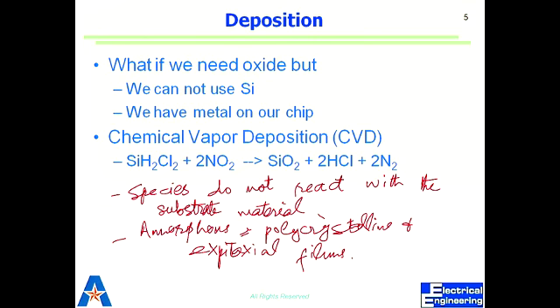This again, upload it here. We have looked at oxidation, right? This is just an example: if you want to have silicon dioxide but we cannot use silicon. In one case we saw, Manisha was talking about where we can oxidize and then we do CVD. CVD is what we do if we don't have too much silicon to spare. Quite often this is the case for SOI wafers, where we have silicon on an insulator and we don't have too much silicon on the top above that buried oxide. If I use this up, I will not be left with enough to make my devices. So what I want to do is instead deposit silicon dioxide.